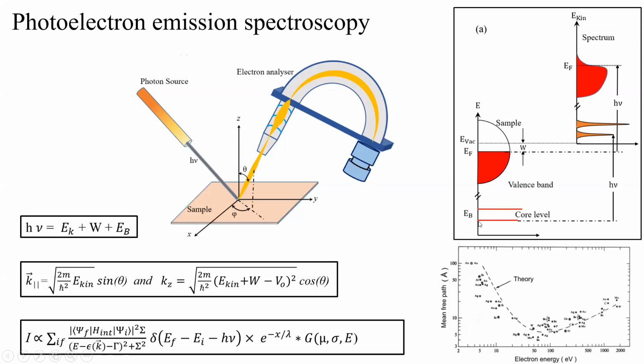So in the atomic case, you actually expect a sharp line. A sharp line means that the states are not dispersive. They have a finite energy value and no k dependence. Like in the hydrogen case, for n equal to 1, you have one energy value. It's not broad. But when you excite these core levels, because of the resolution broadening and the lifetime of the core hole that you have created, you actually get a Gaussian Lorentzian product function in place of this Dirac delta function.